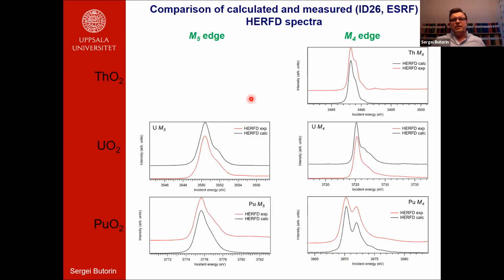Okay, now a comparison between experiment and the calculations. I was actually quite surprised to see such a good agreement, because these are only crystal field calculations without taking into account hybridization effects. But you can see quite a good agreement here, here, and here. For thorium dioxide, these small satellites are not reproduced because, of course, one needs to take into account, besides 5f oxygen 2p hybridization, also the 6d states as well. Those are important for this system.